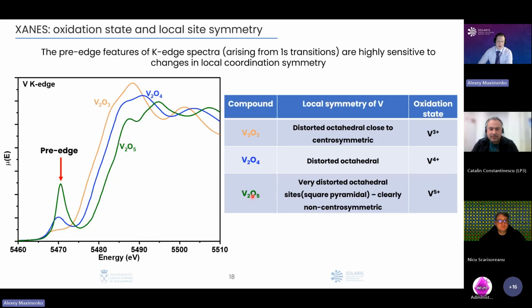As you can see here, vanadium 5 oxide is a very distorted structure. Actually, it is square pyramidal. Vanadium 4 oxide is a distorted octahedral, and here you can see a less intense peak. And vanadium 3 oxide is close to centrosymmetric, and that is why here you mostly have the transition between 1s and 3d, because we know that this 1s to 3d transition is dipole forbidden, but quadrupole allowed, and that is why some probability still exists that you will have this transition.